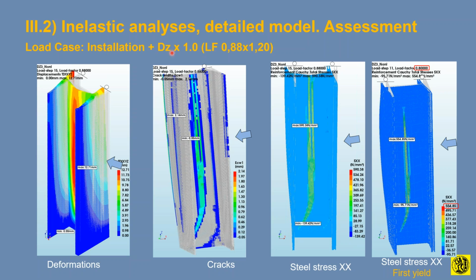Now, in this case, which is installation again times 1, again 88 times 1.2, plus the differential. Now we can see that the full deformation is now 12 millimeters, and it's actually here because of the 3-meter differential between this area here and the remaining. So there is a big out of plane bending of this transverse wall, which should not have been happening if the breaches were not happening.